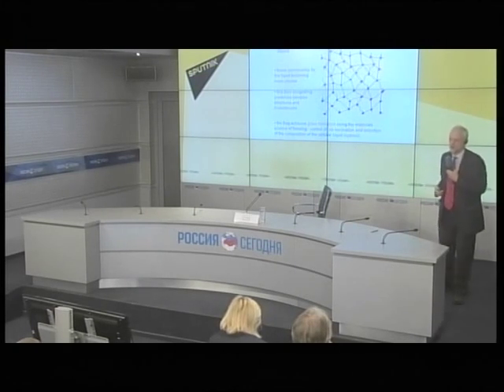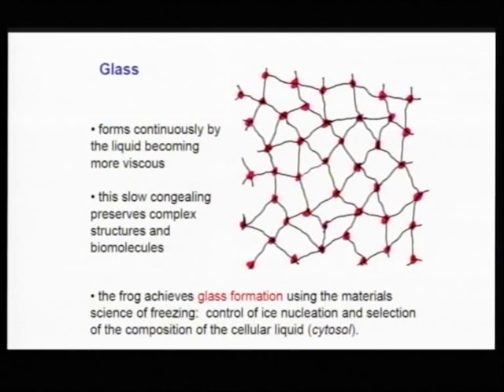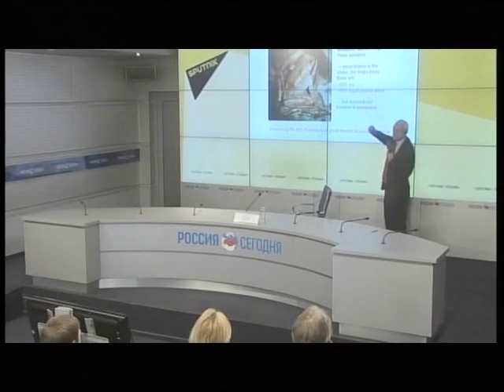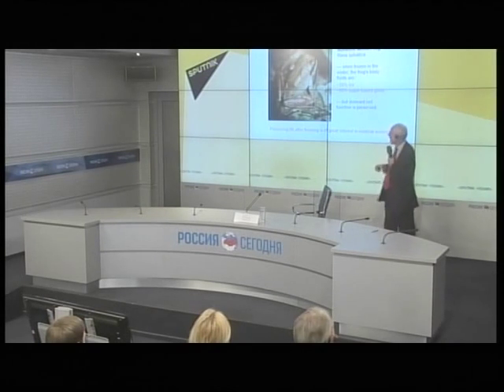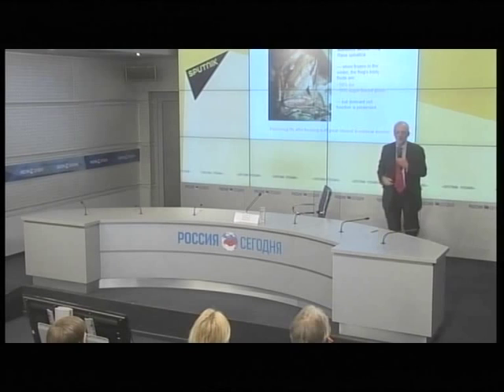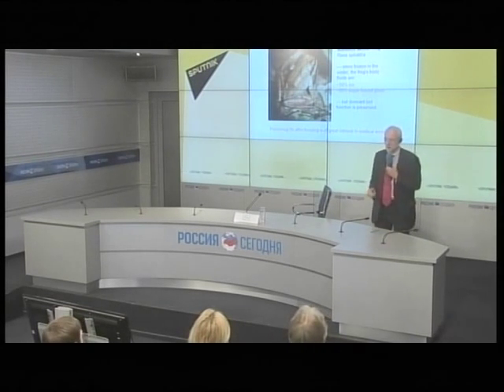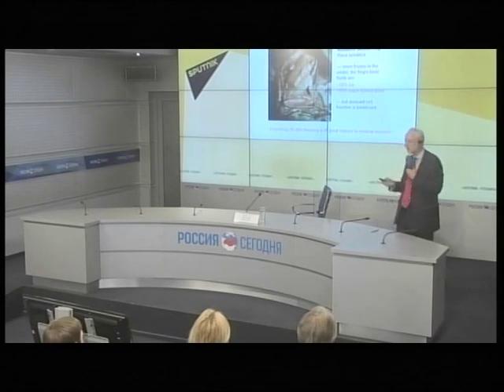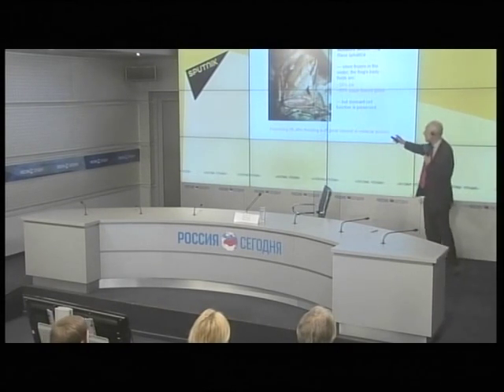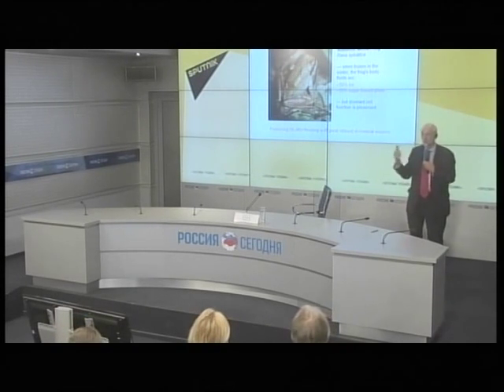Here is an example of a glass. You have a solid structure, but it in some way preserves the arrangement of the liquid. It's formed by gradually becoming more viscous, and definitely not by freezing and forming a distinct crystal structure. If you did form crystals, the cell would be dead. And in the winter, this frog is 100% solid. It's about 50% ice in this tissue outside the cells, and about 50% of this sugar-based glass. Nothing is happening in the frog. It's dormant. But when you put water back in and it thaws out, it comes back to life. So it's clearly of immense interest in medical science, whether it be preserving organs or something else.